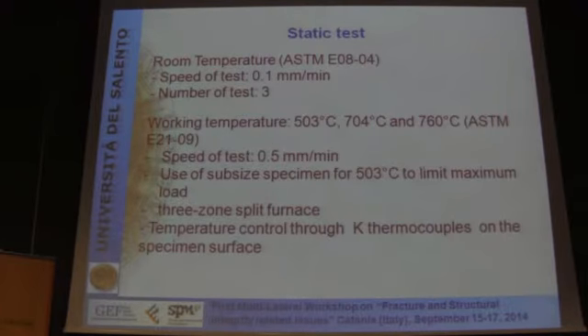Here you can see several details about the static test. We performed a static test at room temperature with a speed of 0.1 millimeter per minute, and we considered the working temperature from 503 degrees to 760 degrees. The speed of the test in this case was 0.5 millimeter per minute. Only in the case of the lower temperature, we used a sub-size specimen in order to limit the maximum load that we obtain during the test.